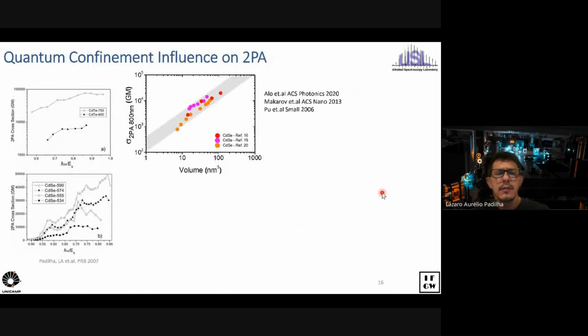However, in our first work in 2007, when I was still in grad school, we realized that that was not actually true. The two-photon absorption cross-section would decrease as the quantum dot became smaller. And the argument there was just that it's a matter of size. It's much easier for you to interact with a basketball than with a baseball, just because the basketball is bigger. So it's much easier for 2 photons to find a basketball than to find a baseball. So the cross section for a bigger ball is higher than for the small ball, and that should scale with the volume because the interaction doesn't have to be on the surface. It goes through the sample, through the whole volume of the quantum dot.